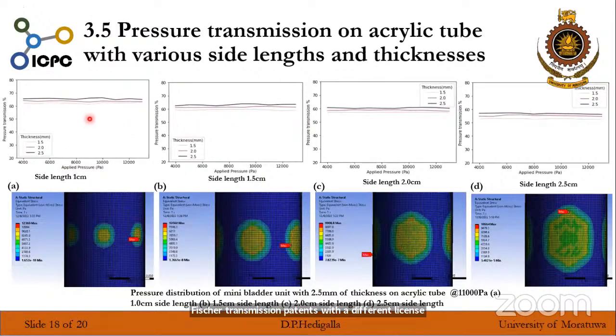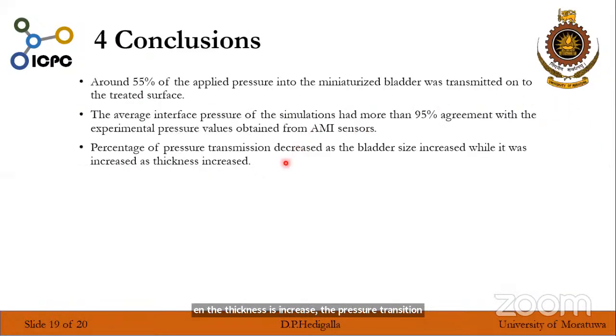And here is the pressure transmission percentage with different sizes. As you can see here, once the side length of the mini bladder was increased, the pressure transmission percentage was decreased. However, for each mini bladder, when the thickness is increased, the pressure transmission was increased. And those are the conclusions.